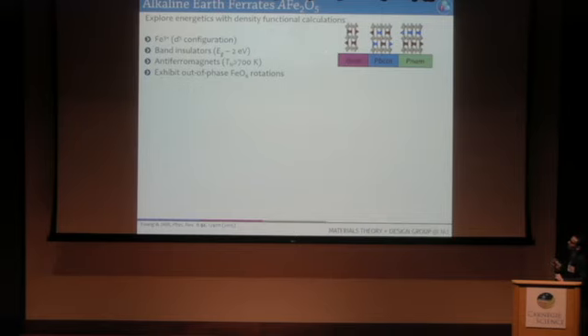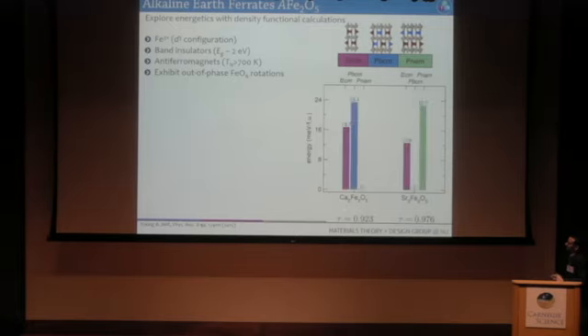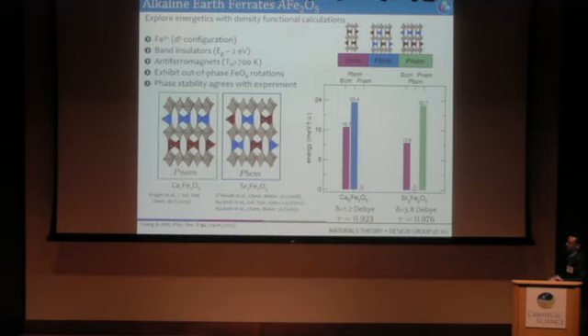And these are the three polymorphs we want to consider. And we've been looking at the energetics, the phase stability of these materials. So if I take calcium ferrite and perform a density functional theory study, what I find is that the lowest energy phase is this Pnma one. If I look at strontium ferrite, the lowest energy phase is this PBCM one. And so the stability of these phases is actually in quite good agreement with the experimental reports.